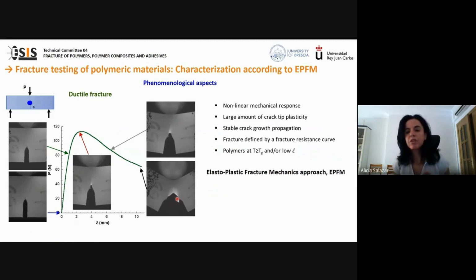Next, I'm going to describe the fracture characterization according to the elastic plastic fracture mechanics approach. The phenomenological aspects are non-linear mechanical response, as observed in this load displacement record of a typical ductile fracture in polymers. Large amount of crack tip plasticity can be observed in these photos as a whitening region ahead of the crack tip, as well as crack tip blunting and stable crack growth. The fracture property in this case is not a single value. It's a fracture resistance curve in which the fracture parameter is a function of the crack growth extension.